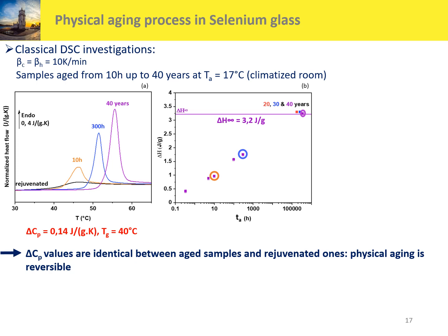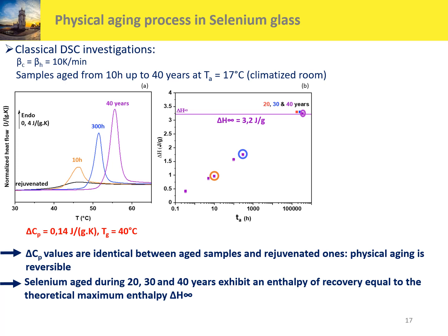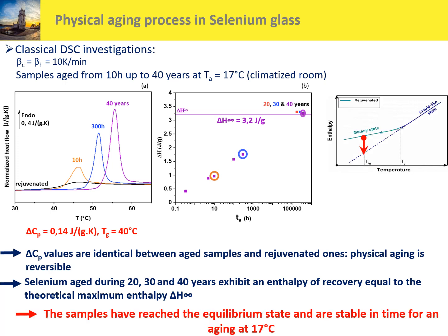We can observe that the delta Cp values are identical between aged samples and rejuvenated ones, so the physical aging is reversible. We observe that the selenium aged during 20, 30, and 40 years exhibits an enthalpy recovery equal to the theoretical maximum enthalpy, noted delta H infinite. It is presented here. So we can conclude that the samples have reached the equilibrium state and are stable in time for an aging at 17 degrees C.